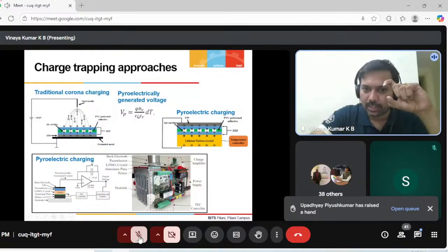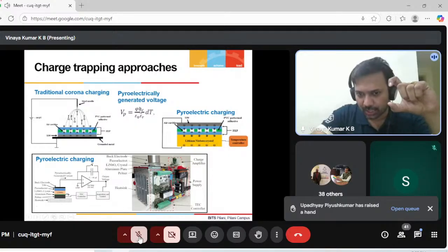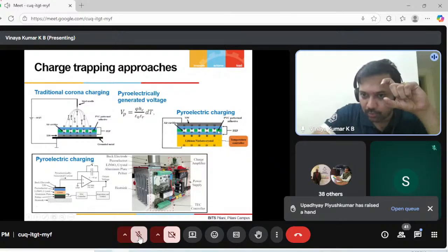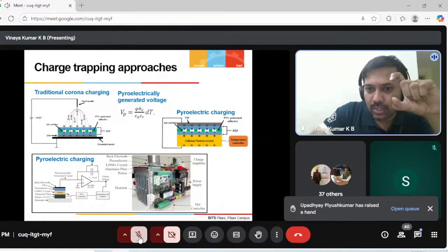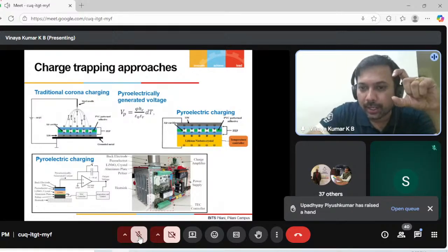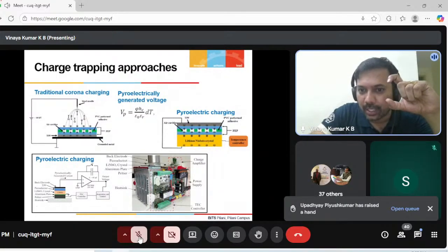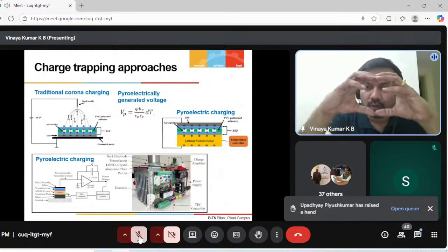As you can see, this is the equation. The surface potential depends on delta T, the dielectric constant, the pyroelectric coefficient of the material, and the thickness of the crystal. Using this crystal, as you can see, this is where we placed our FEP, fluorinated ethylene propylene, with the voids. Because the crystal generates a very high electric field, and we know there are air molecules in the voids we created, we try to break down the air molecules in the voids and generate positive and negative charges. That's how we are able to trap the positive and negative charges.